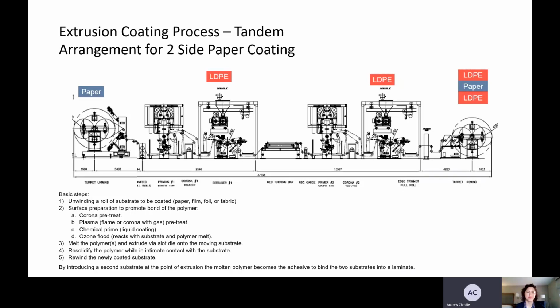For low density polyethylene, commonly run, it's coated on in a single layer. We can then turn that over. We can then pre-treat this again and then coat the opposite side. So this would be a typical configuration for an extrusion coating line, and that would include unwinding, pre-treating, the coating station where the polymer is applied, and then rewinding this product back up.